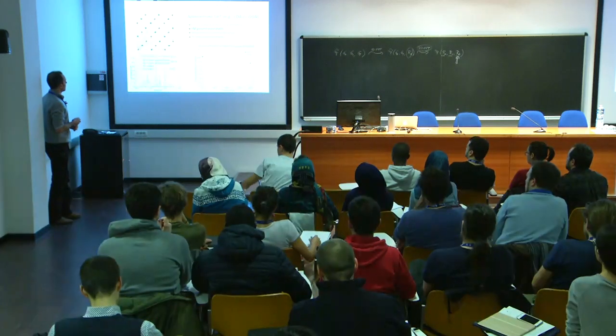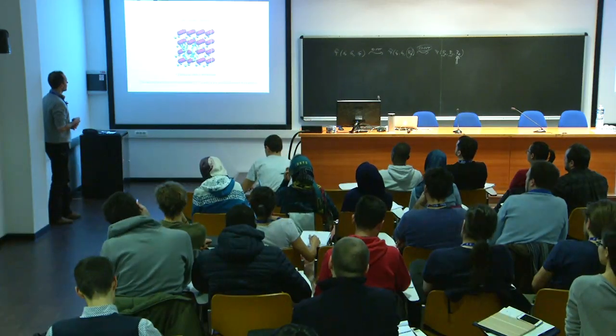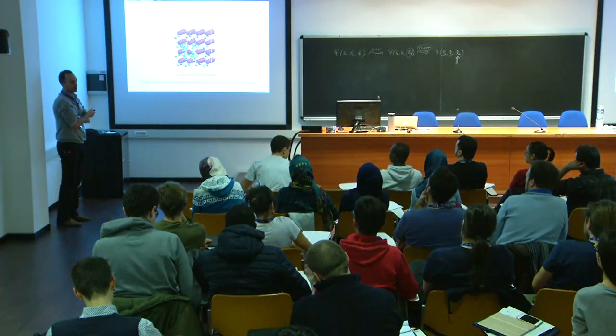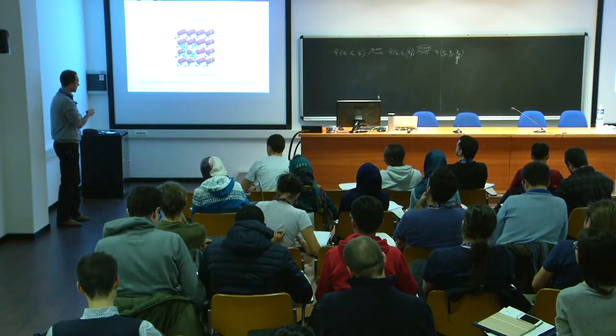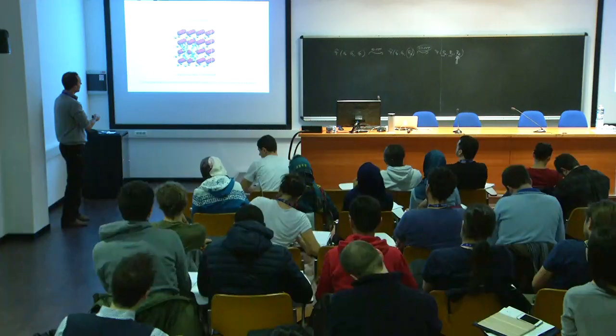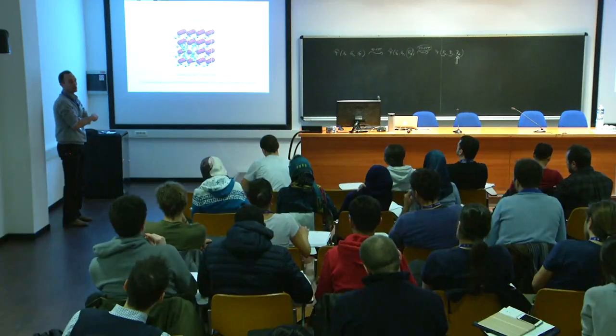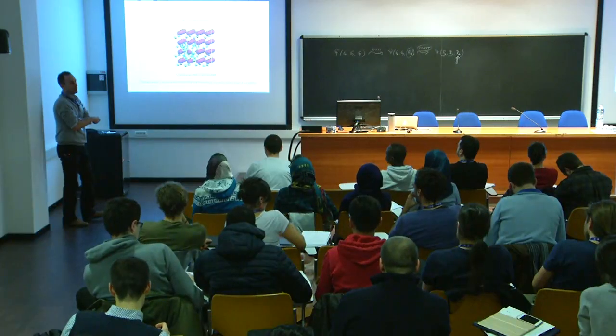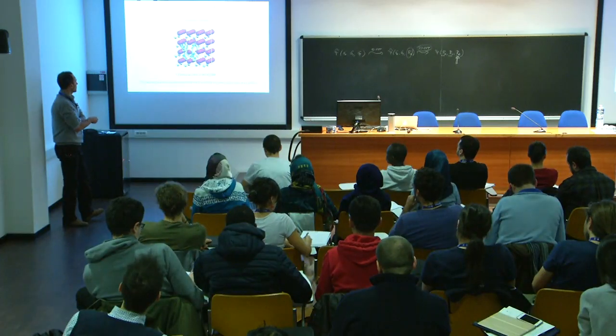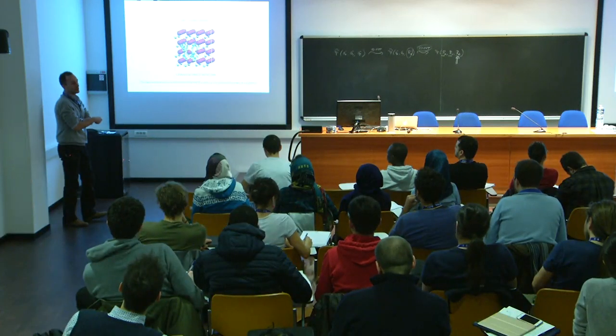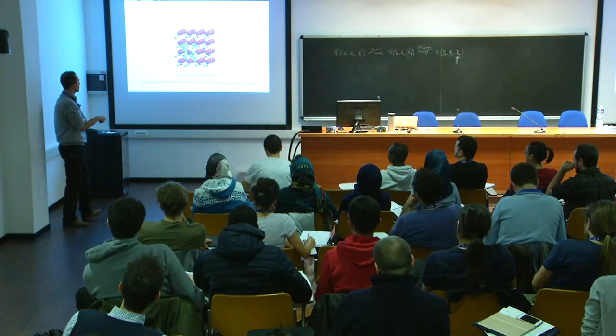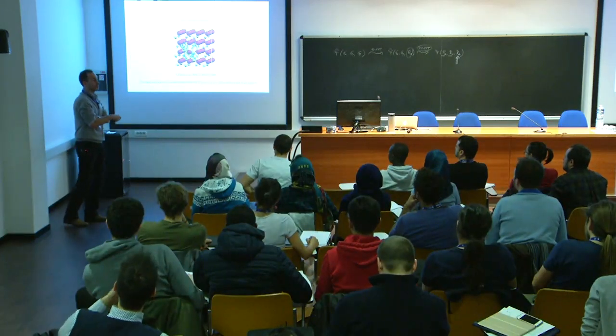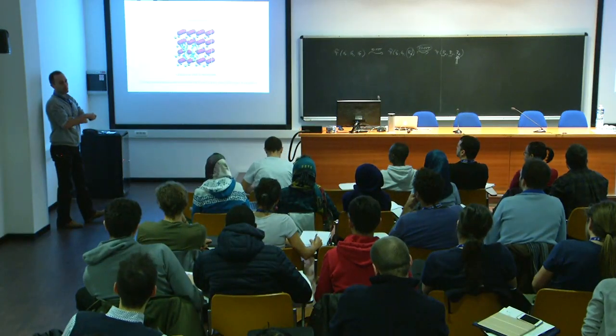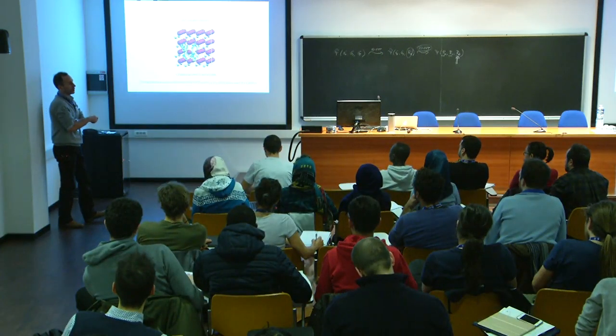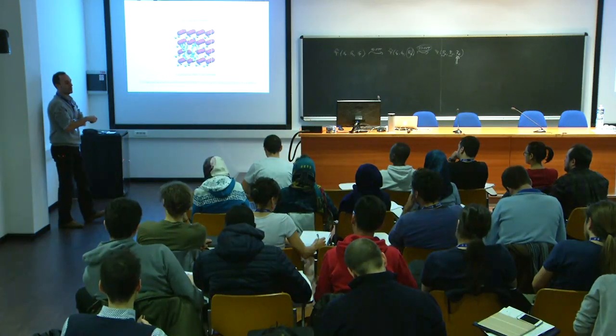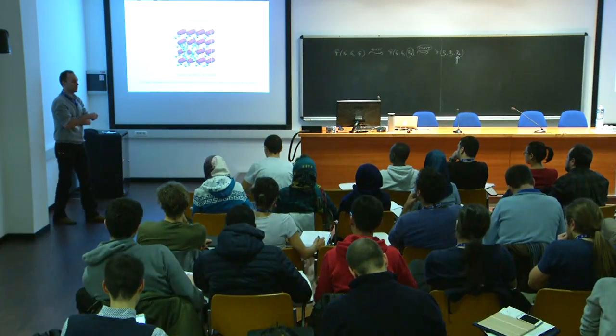So this is one example of a problematic case. Another one is the localization of electrons over defects. So this is cerium O2, and here you get an oxygen vacancy, so there's one oxygen missing. You would expect that the two electrons that are left behind by the missing oxygen would localize on two of the four cerium atoms that are around this oxygen vacancy. It's not the case. You see the charge density of the two electrons left behind is delocalized instead over four cerium atoms, in a sort of metallic state. This is again not consistent with the experiment.